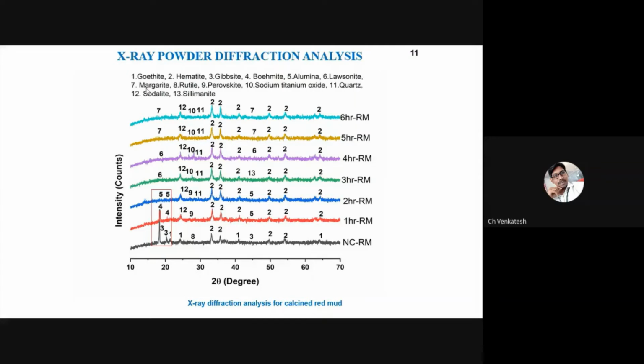After heating 1 more hour, the boehmite is converted into the alumina. Initially, gibbsite converted to the boehmite, and boehmite converted into the alumina. But throughout the XRD peaks, iron oxide is a stable one, because the existing literature also mentions that whenever you calcinate the red mud, only after 1600 temperature is there a chance of a transformation in